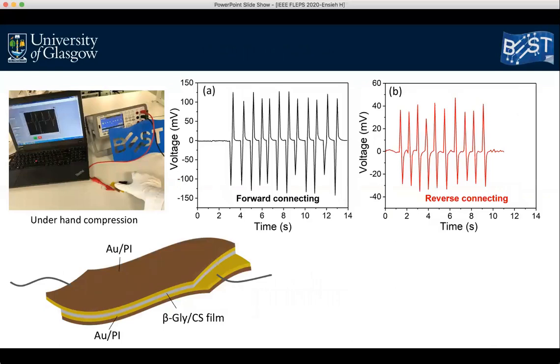And this figure shows the output voltage generated from the device when it was just touched by hand. A repeated compression and release process showed the sensor responding uniformly with periodically positive and negative alternation. In addition, the output voltage was measured after reversing the electrode connection, and the signal sign was reversed, and it demonstrates well that the response is coming from the piezoelectric effect of the film.